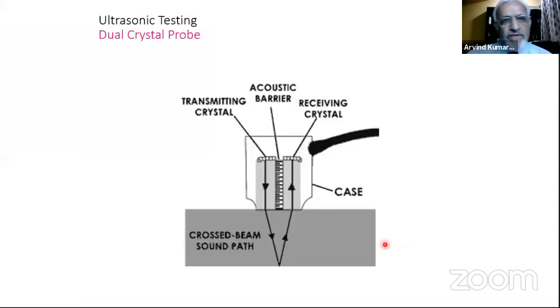Now, if you have a dual crystal probe, this is how the construction is. You have 2 crystals here, one acts as a transmitter, the other acts as a receiver. And there is a barrier inside so that they don't crosstalk between each other. And then the rays go like this. As you can see here, it doesn't come directly perpendicular as in the case of a single crystal. It has some sort of angle.